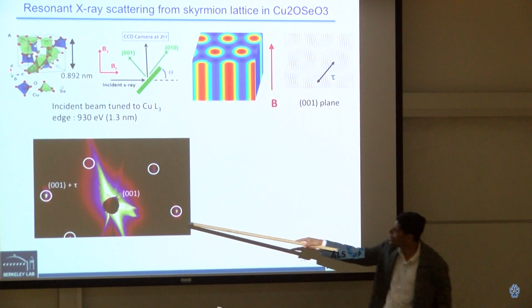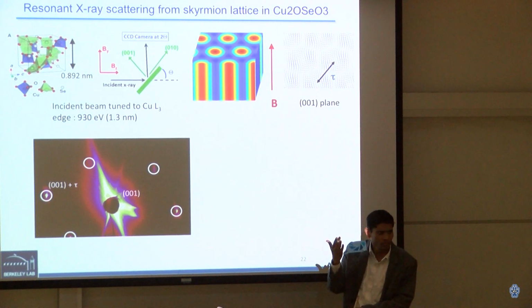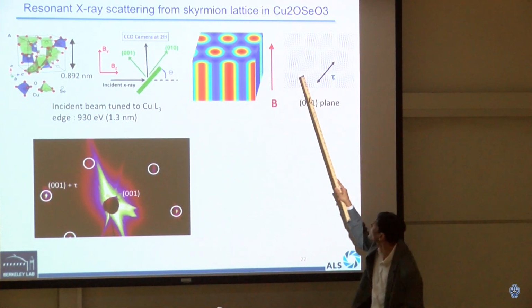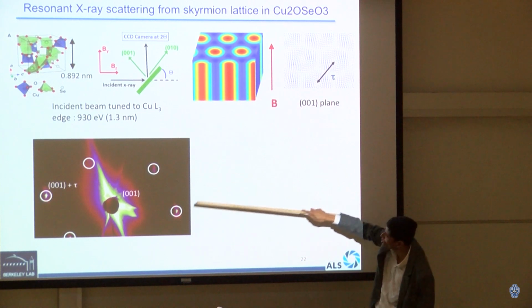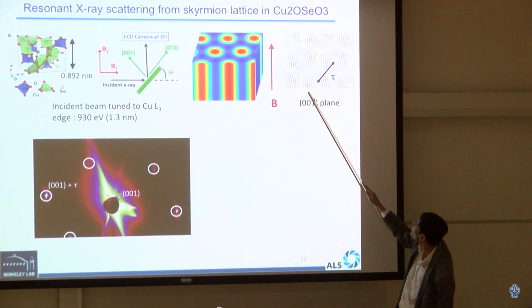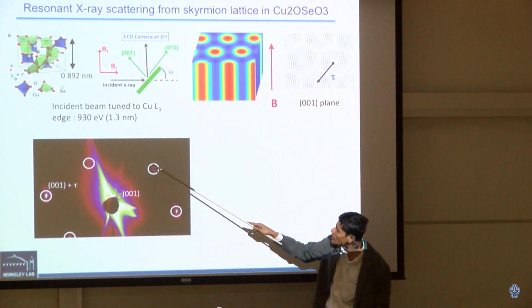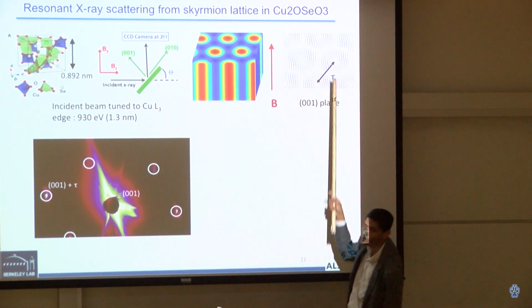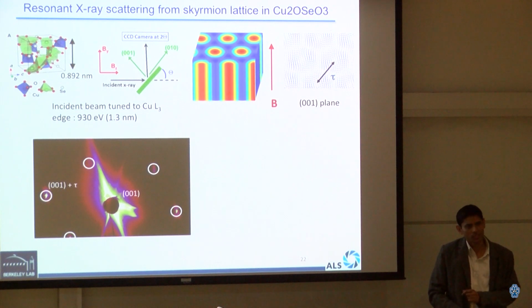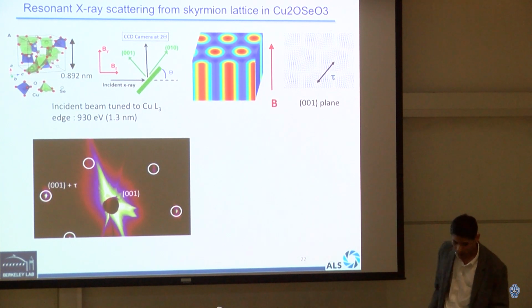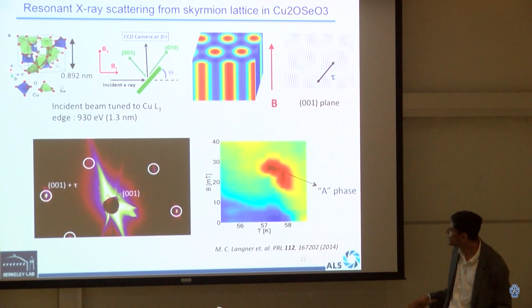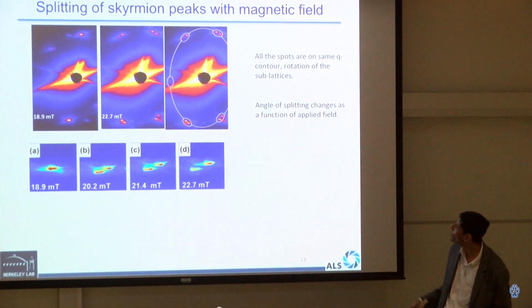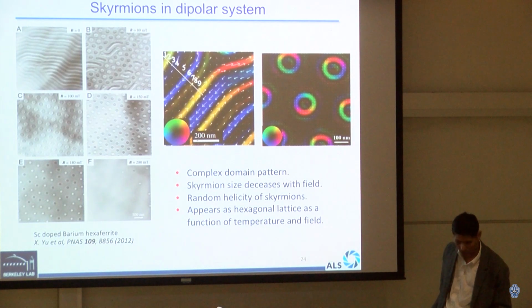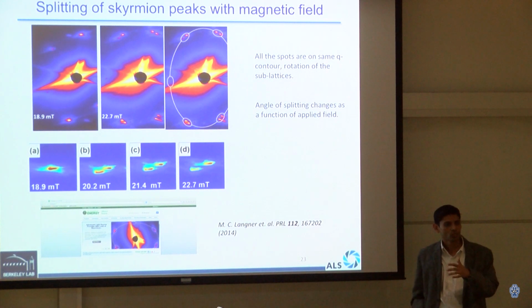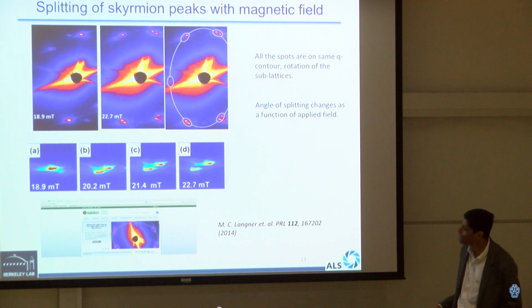So that's exactly what we see. This is the 001 Bragg peak. And with respect to that Bragg peak, remember, the Bragg peak is in the z direction. So it gives a Bragg peak, and within the Bragg peak, at a distance tau, it sees the spots due to the swirl. And this is the first demonstration that X-rays can see skyrmions. This is what Matt did, and we then drew out the phase, and this is the famous A phase again. This exact textbook, and then we did some other things just to show that we have done a diligent job. So that's what got us into skyrmions, and this was a few years back.